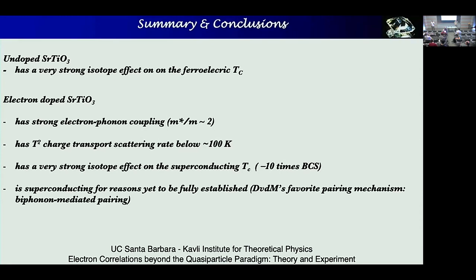But my question is, there was also recent work, I forget who, that I know is also in the paper, where they found there is a finite Q, very soft phonon that comes from the hybridization of the acoustic transverse and the optical transverse mode. There is a hybridization, and they get very soft. And I think Pierre Littlewood would even estimate and said that maybe the system is closer to the finite Q instability than to the ferroelectric. So just to see if you have any thoughts about this idea and how it plays out with the phenomenology of this compound.